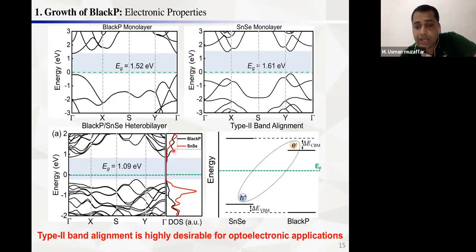You can see in the total density of states, at the conduction band minimum the dominance is from the black phosphorene, and at the valence band the density of states is mainly dominated by the SnSe. So this is the characterization of the type 2 band alignment. So these are the conduction band minimum of the black P, and this is the valence band maximum of the black P, and you can see that they are lower in energy than that of the SnSe. So the electron in the conduction band minimum of black P and a hole in the valence band maximum of the SnSe, if they have strong enough energy, can form an electron-hole pair. And you can see that the electron-hole pair is highly desirable for practical applications.